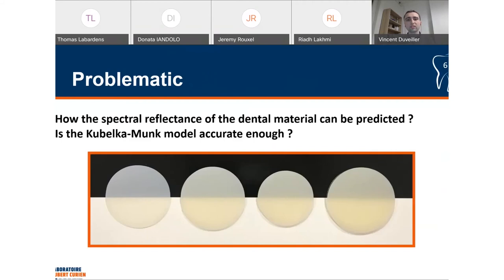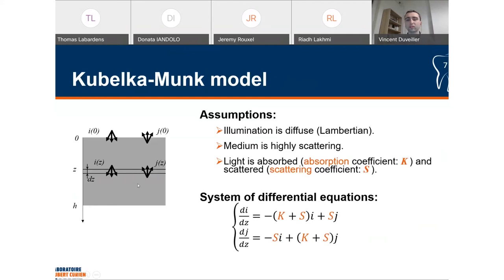So the objective of my work is to be able to predict a dental repair, and here I tried the Kubelka-Munk model and assessed its accuracy to predict the reflectance and transmittance factors of a dental material in a very simplified case where the samples are flat. So it's a very simplified study within the general problem. The Kubelka-Munk model is a well-known model for its simplicity. It considers two light fluxes, one going down and one going up inside the material.